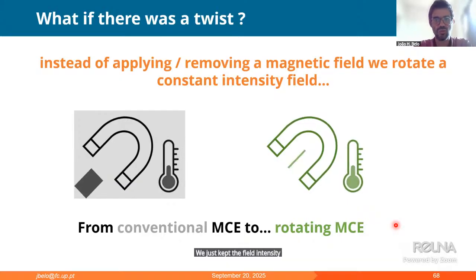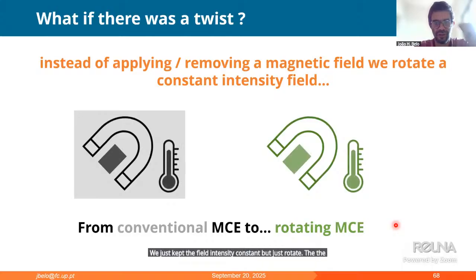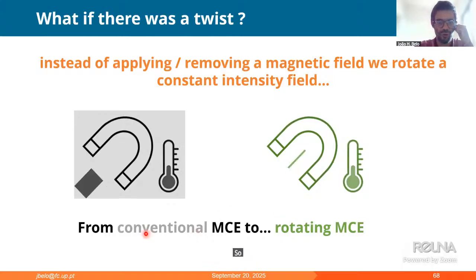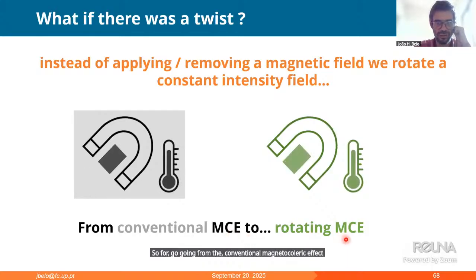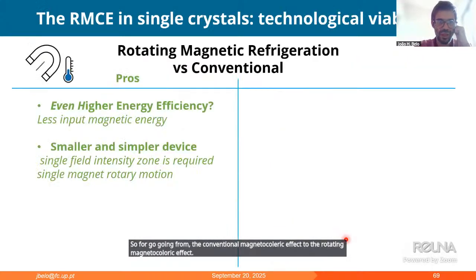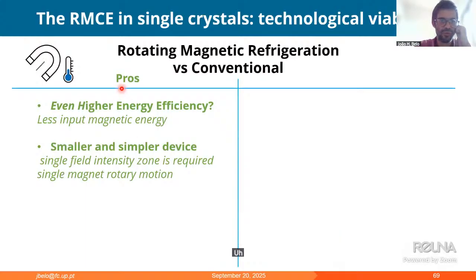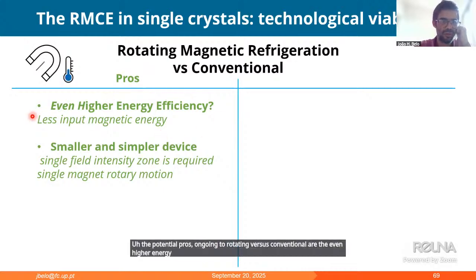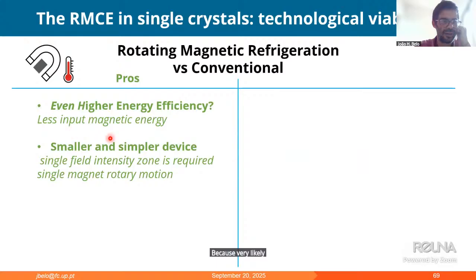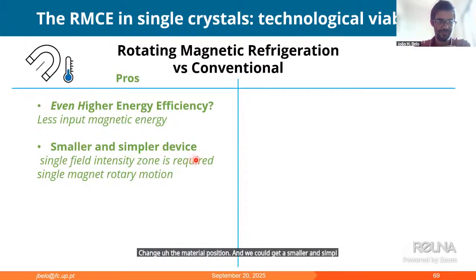But what if, instead of applying and removing a field, we kept the field intensity constant and just rotated the field vector? So, going from the conventional magnetocaloric effect to the rotating magnetocaloric effect, the potential pros are an even higher energy efficiency, because very likely we'll need less input magnetic energy to change the material position, and we could get a smaller and simpler device.